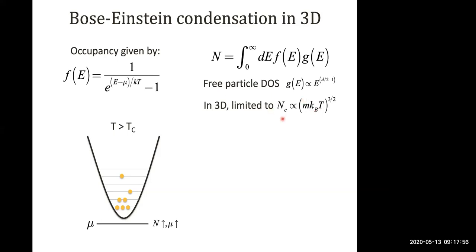So this critical density at which you can no longer fill the excited states is proportional to a power of the effective mass of the particle and the temperature. So a very low effective mass leads to a very low critical density, or equivalently, for a fixed number of particles, you have a very high critical temperature. So schematically, what happens is that you have some number of states which you need to fill. As you continue to add particles, you move the chemical potential upwards.